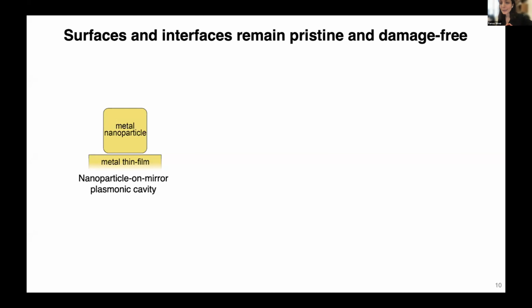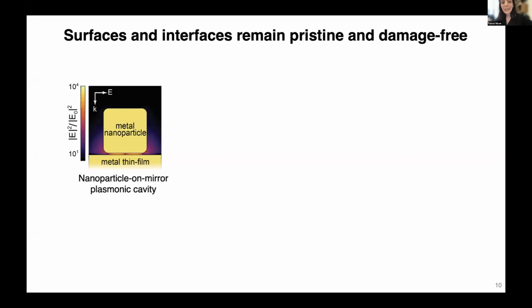So for us to be able to characterize the pristine nature of our process, we used our process to fabricate these nanoparticle-on-mirror plasmonic cavities, which allow field enhancement, and as a result, Raman enhancement of any material that is placed in the gap. We use this Raman enhancement to probe the material on the surface, and as a result be able to make a conclusion about whether our processing has introduced any damage to the surface.